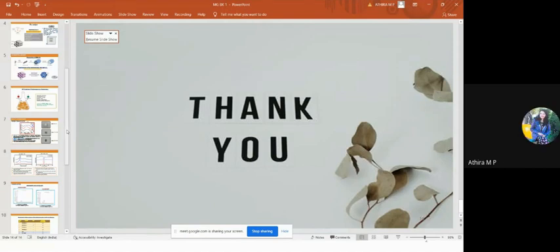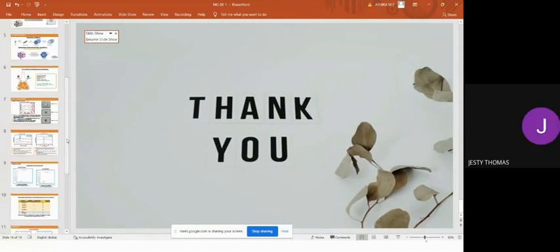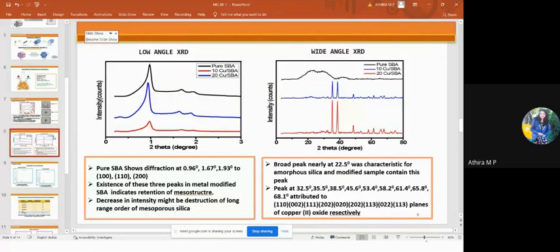Yeah. Okay. Then can you take the low angle XRD? Yeah, that slide. Okay, here in this low angle XRD, there is a slight shift in the peak at 10 copper SBA, that second sample. Why has that shift come in the 2 theta angle? That is due to the copper incorporation, ma'am.